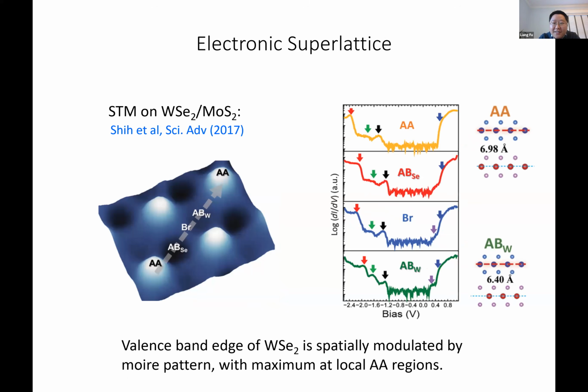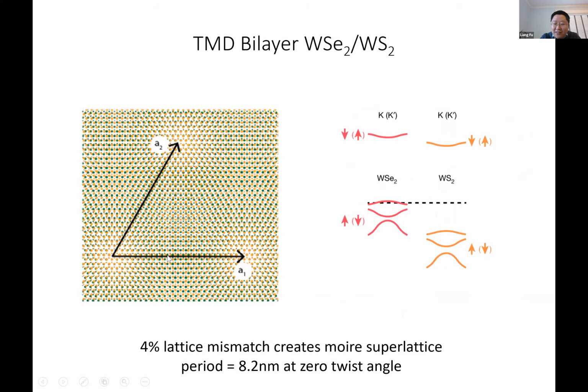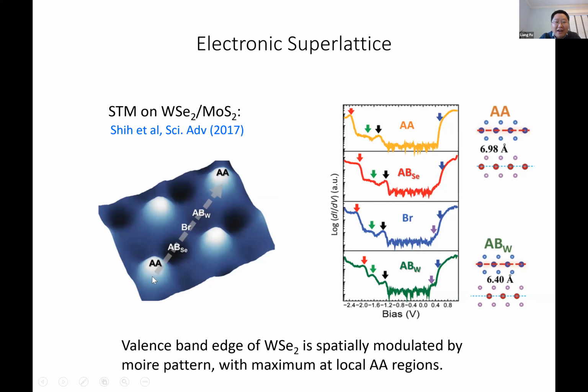And this is seen early on from STM experiments on WSe2/MoS2, a slightly different combination of materials. And what's shown here is a topography image. And you see that depending on where you are within this Moiré unit cell, there are different local stacking arrangements. And the height, the separation between the two layers, depends on the local stacking, as well as the electronic spectrum. So shown here are the STM tunneling spectra. And here, for example, you can see that the valence band edge is spatially modulated by the Moiré pattern, and the maximum of the valence band edge appears at the local AA stacking where the two layers are aligned. Okay, so in particular, the AA region and the AB region, the so-called AB region in this notation, are going to be important for our discussion later.